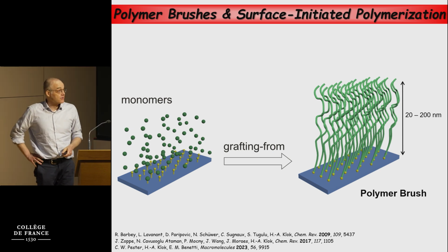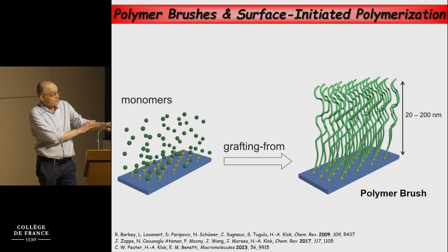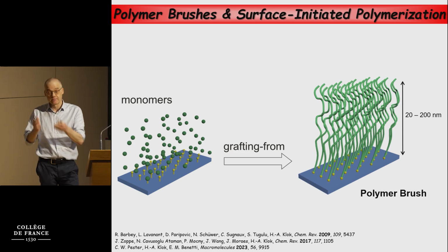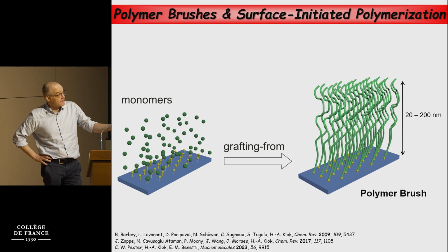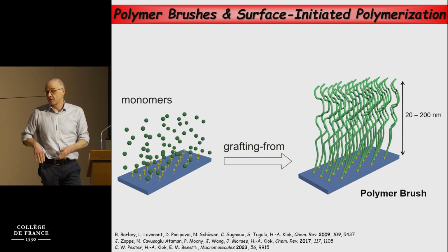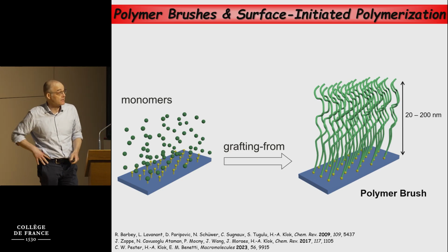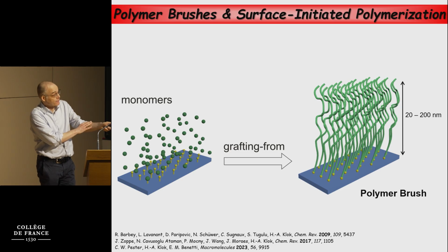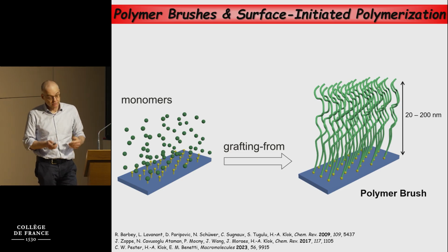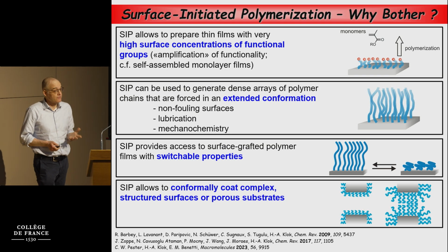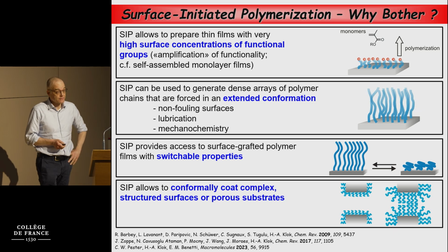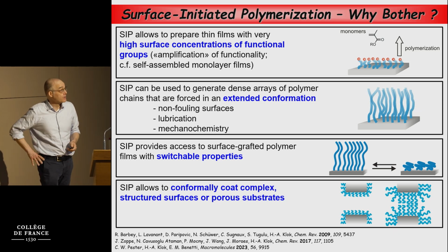And the unique feature of this is that these polymer chains are tethered via one chain end to the substrate. And since we grow them in a bottom-up fashion, we have the possibility to anchor these chains at distances which are much, much smaller than the radius of gyration, as a consequence of which we can enforce a stretched chain conformation. And this surface-initiated polymerization approach is very interesting. It has a number of unique attributes.